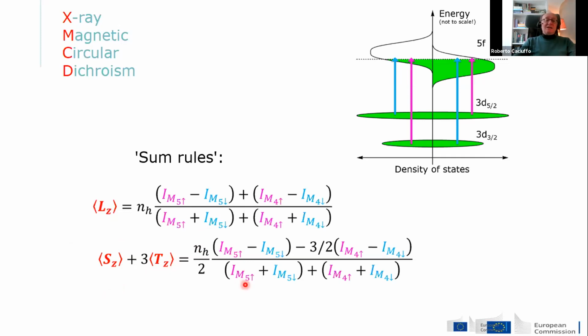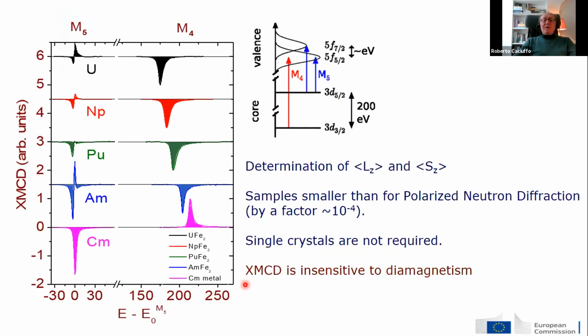Experiments have been done on a number of compounds with different symmetries, different characteristics, different physical behavior. For instance, here you see the signal obtained for actinide-iron-2 compounds from uranium to americium compared with the signal measured for elemental curium. A visual inspection of these spectra immediately tells basic properties of the atoms. For instance, you see here that for the light actinides, the peaks have the same sign.